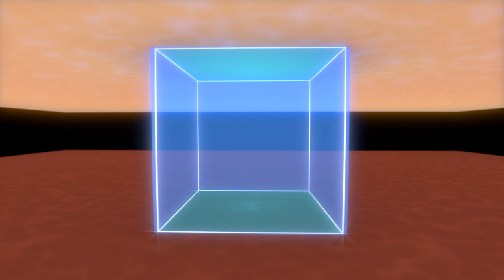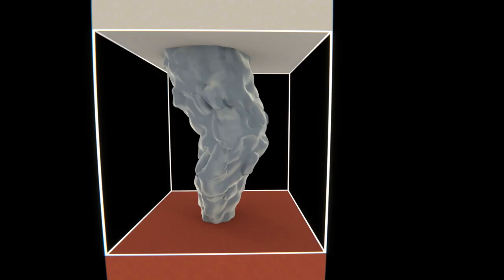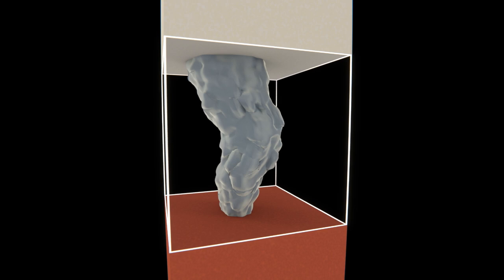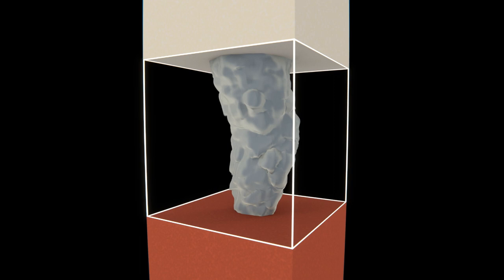Grain boundaries have been considered within the simulation domain. In this region, the activation energy for the Frenkel pair generation, that is, the oxygen vacancies and oxygen ions generation, is lower than in the rest of the dielectric.